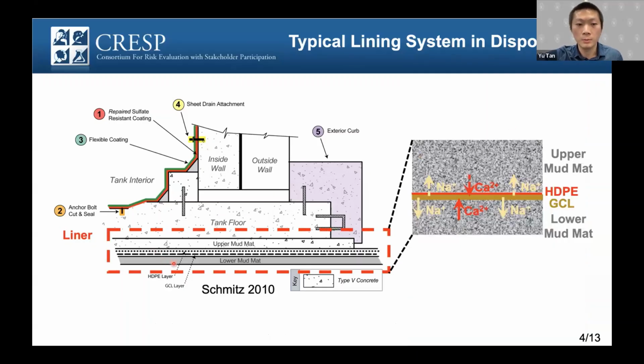In the lining system, we use GCL as a hydraulic barrier because GCL is always used as a hydraulic barrier in landfills. Our experience in landfills told us that if the GCL is hydrated in dilute solution, it becomes very impermeable, so it can work as a hydraulic barrier to intercept the leachate. But if the GCL is hydrated in a calcium-rich environment, the GCL will yield a very high hydraulic conductivity. It is not able to work as a hydraulic barrier.